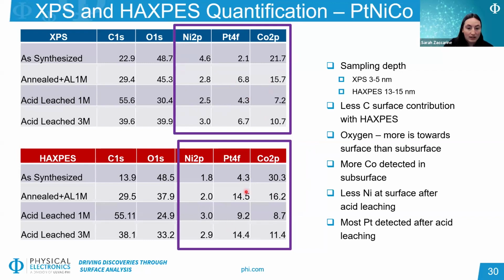We're detecting generally more platinum with the chromium HAXPES source in the subsurface than we are with the XPS source, and with the XPS source we're detecting more nickel. So this suggests that there might be more nickel towards the surface, slightly more platinum and cobalt present in the subsurface. And again, we see changes with each of these different post-processing treatments.